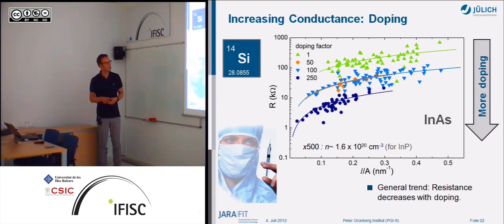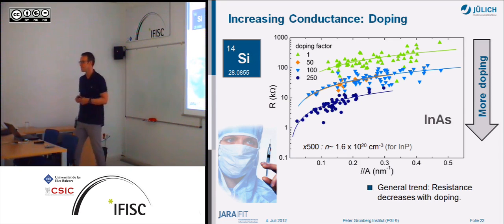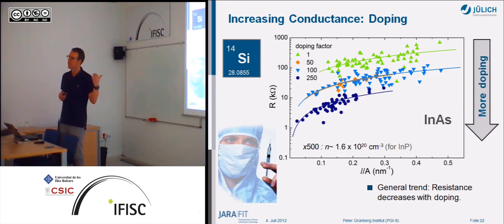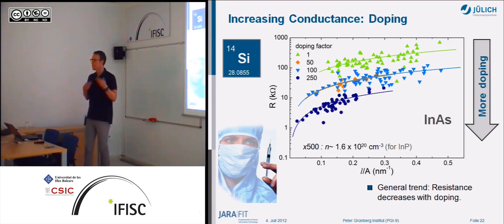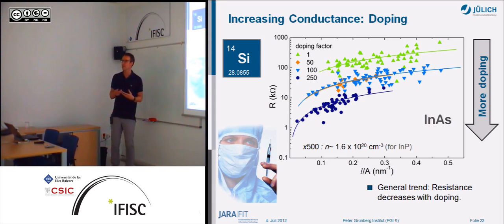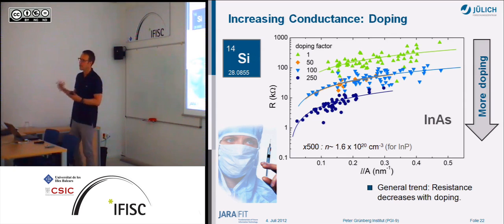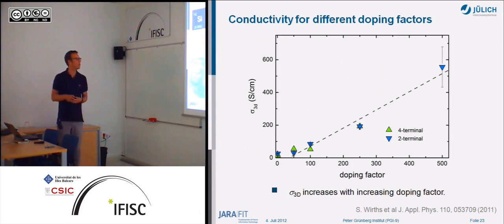What is shown here is the length, so the longer the nanowire is, of course, the larger the resistance gets. But what you can see from that is that if you dope the nanowires, doping is working. What is not trivial. Yeah? You have to prove that at the beginning that you are able to increase conductance by doping, which is for these nanowires not clear from the beginning.